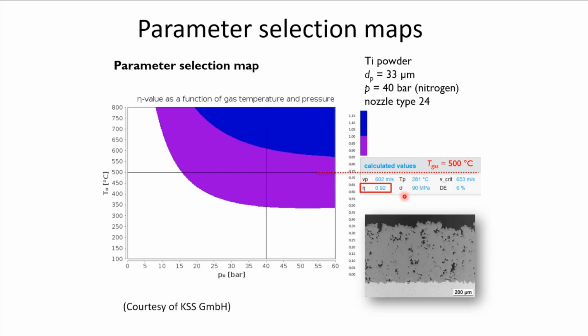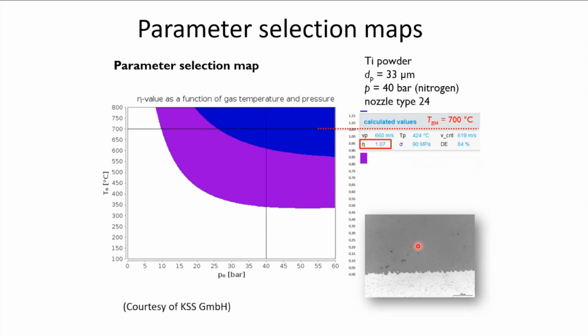And you see that if eta is less than 1, then we end up with a porous titanium deposit. Whereas if you increase that to values above 1, then you get rid of much of those porosities. So this is the benefit of using that eta idea.